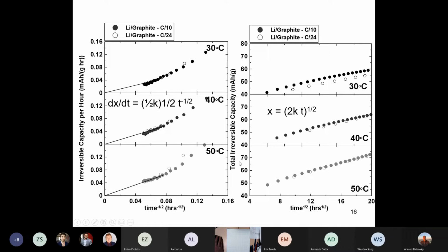And in this case, like I say, it only depends on time. It doesn't depend on the C rate of cycling. So both C over 10 and C over 24 data lie along the same exact behavior. The slope of these curves can be used to extract the rate constant K. And you can see that the slope gets greater as the temperature increases because the SEI growth rate gets worse and worse as the temperature increases. Okay, so it's a good chance here to just stop and talk about this if anyone has any questions. So let's do that.